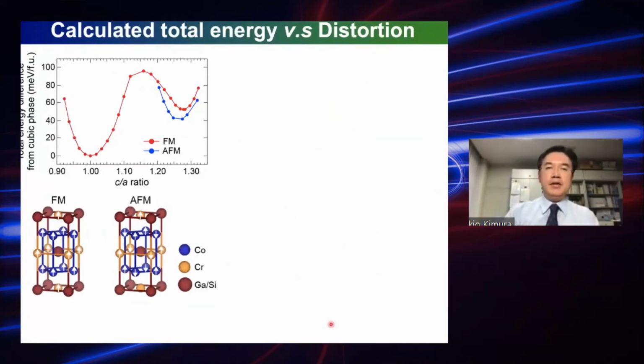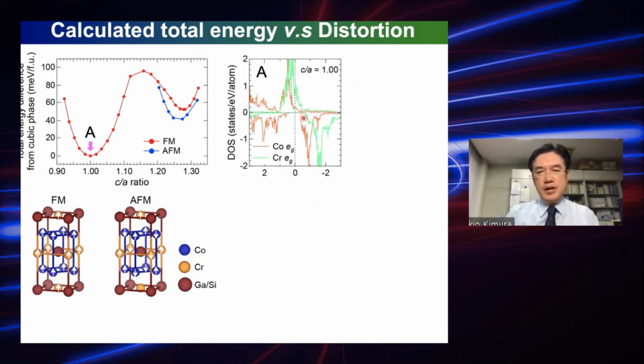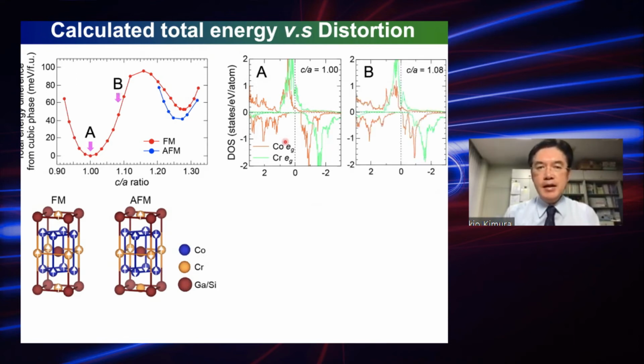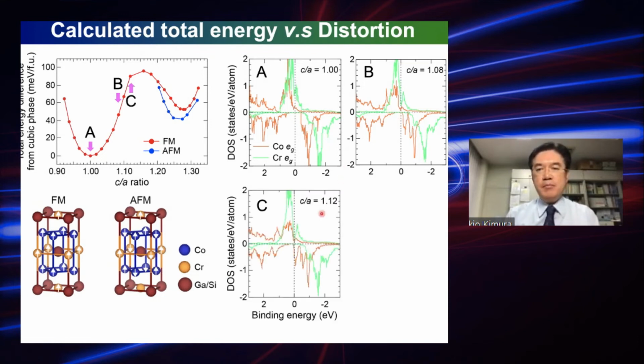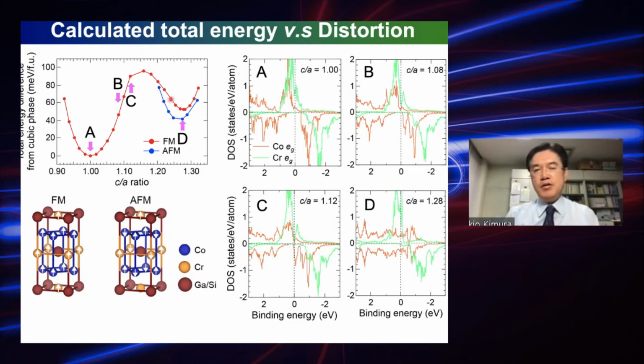Okay, and here's the calculated total energy as a function of c over a. In the cubic phase, c over a is 1. You see the half metallic gap again, and this minority spin gap is made mainly by cobalt eg states. When you increase the c over a ratio, the half metallic gap becomes a little smaller. At 1.12, you see there is a sharp peak in the minority spin gap, so the half metallic gap is already collapsed. In the local minimum at c over a of 1.3, you see some flattened density of states in the minority spin channel.